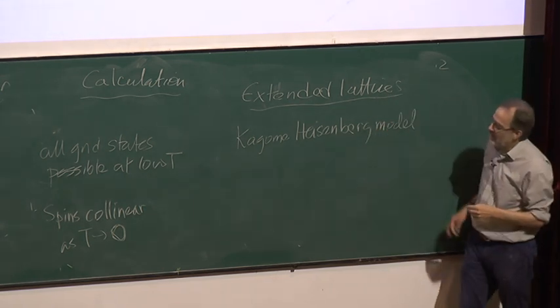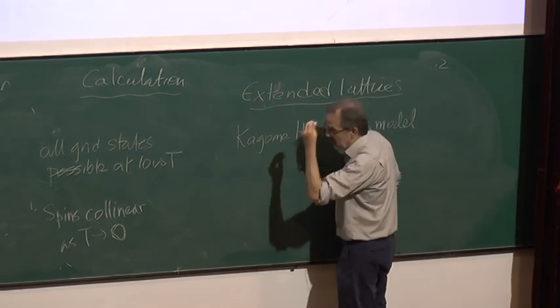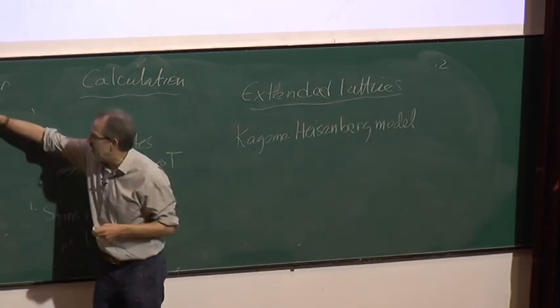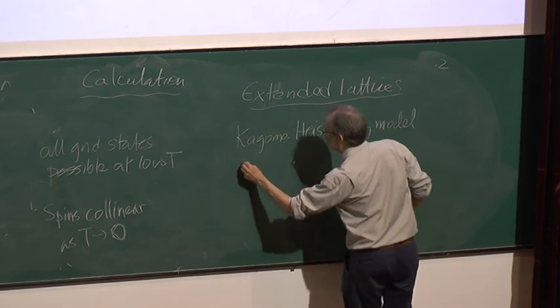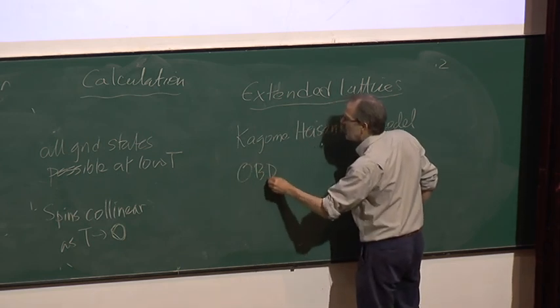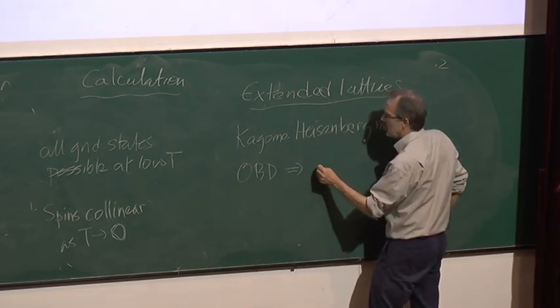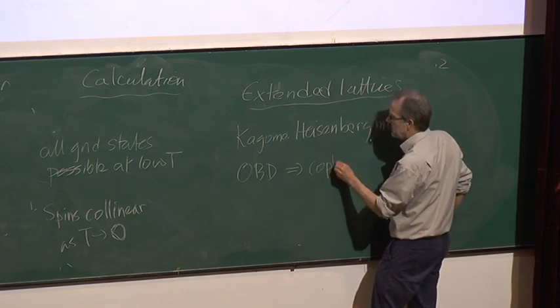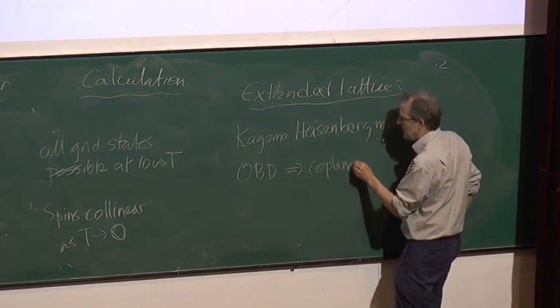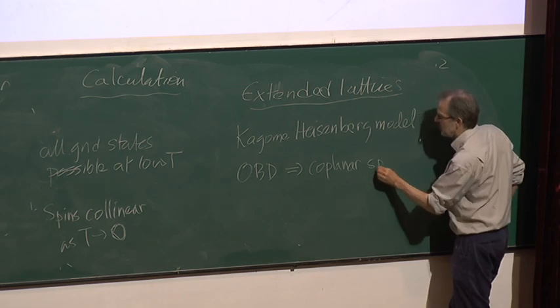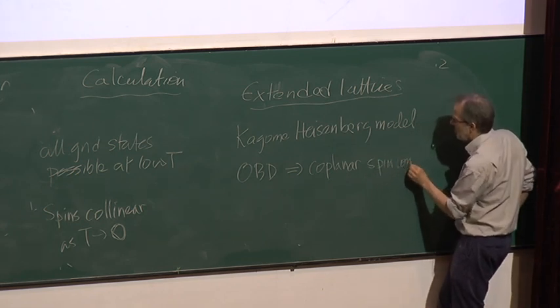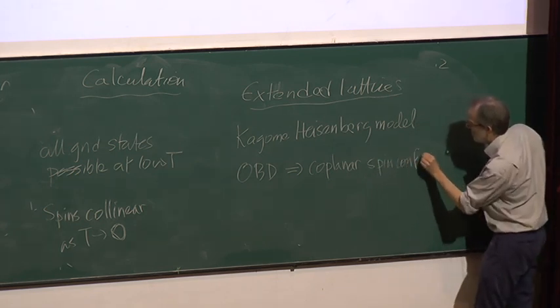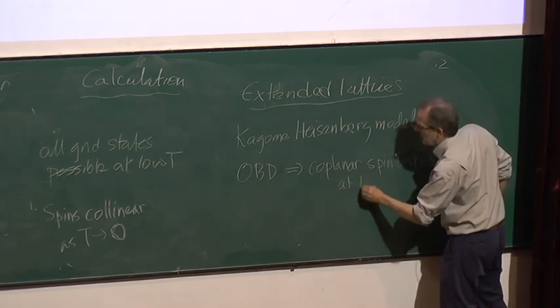So the Kagome-Heisenberg model is an example of a system where you do get this order by disorder. And you, in fact, get coplanar spin configurations at low temperature.